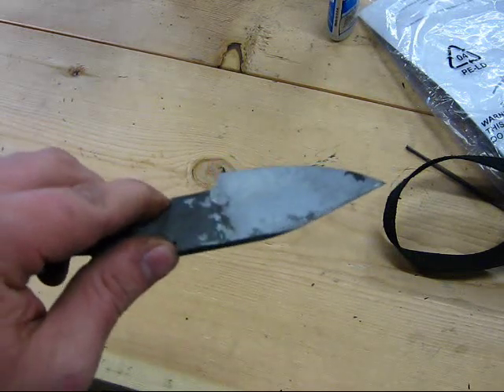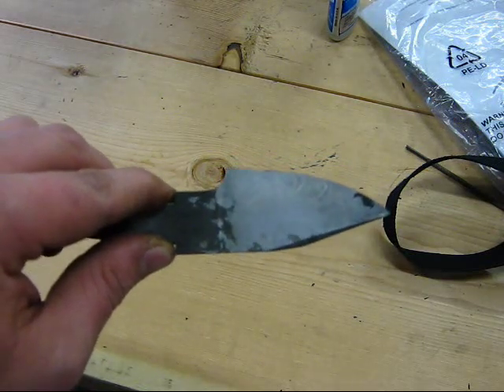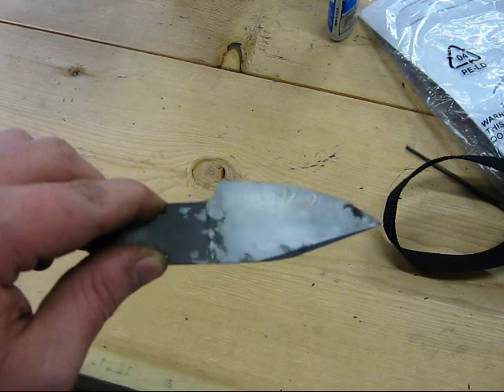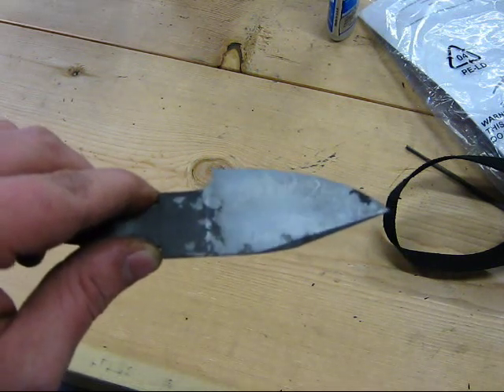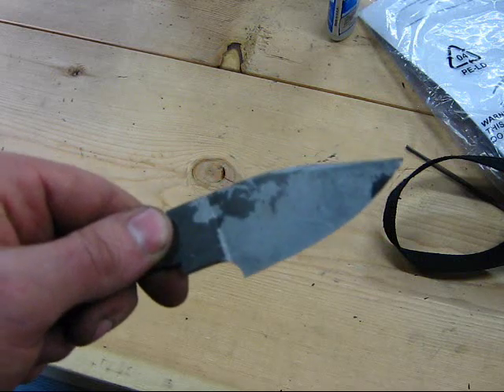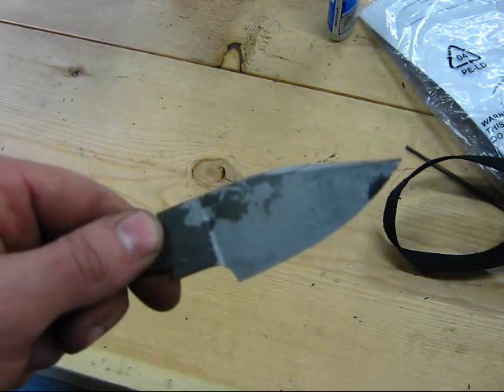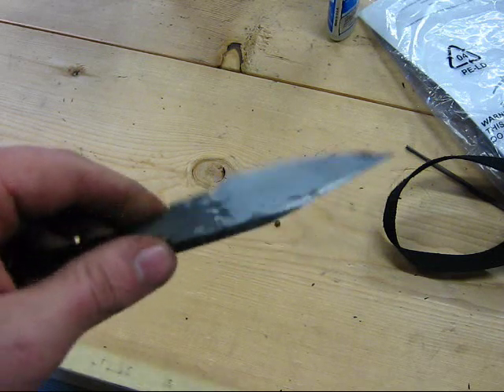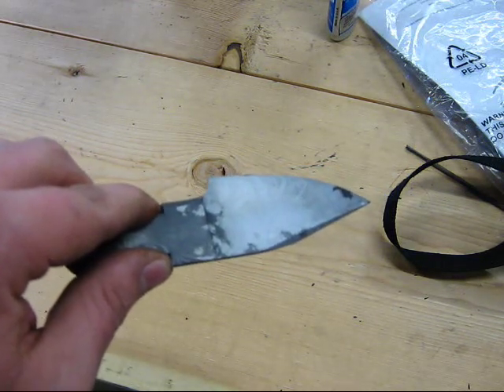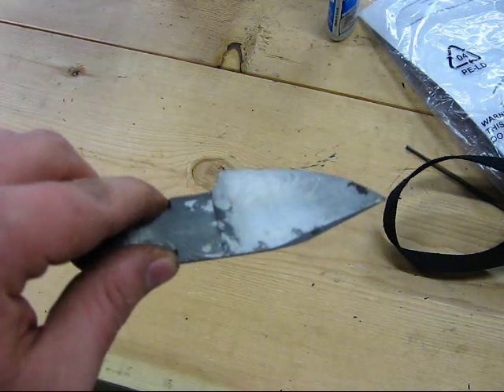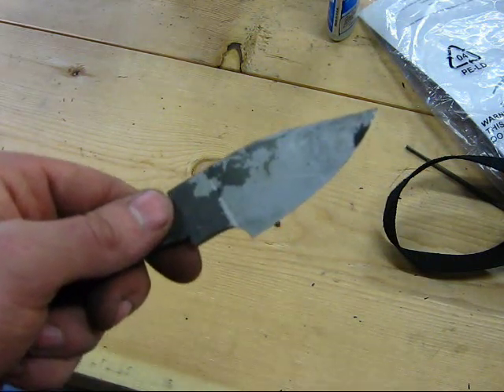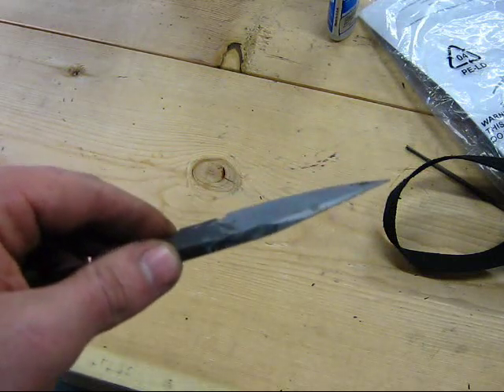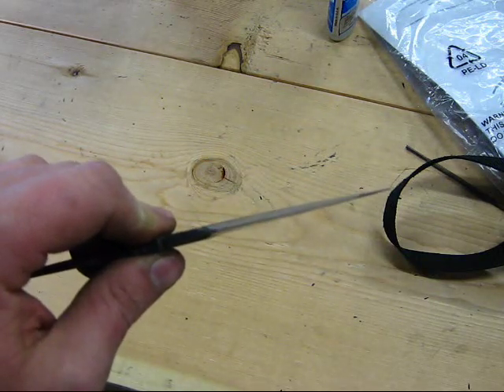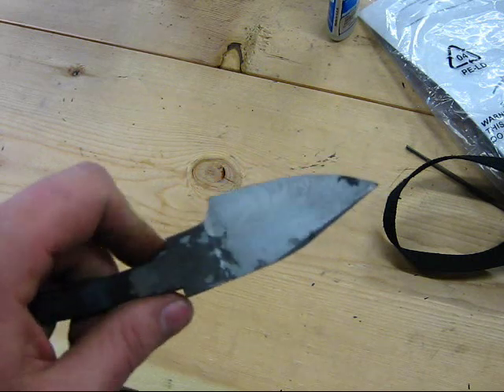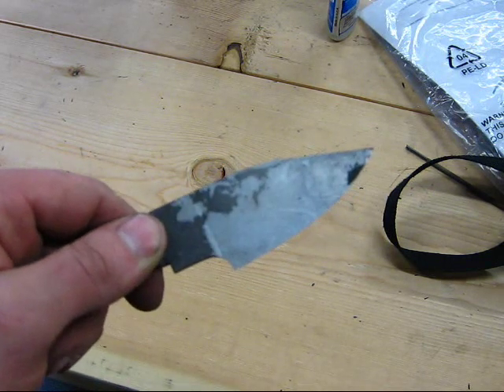But what this does is it allows some of the trapped carbon atoms from within that martensitic microstructure to kind of escape, and the microstructure of the steel relaxes, if you will, enough that it increases the toughness and makes this knife very hard to break and very hard to bend. So it gives it a lot of elastic properties. So if you deform this knife, as in flex it or do something like that, rather than bend and take a set and permanently deform, it will rebound back to its original position.